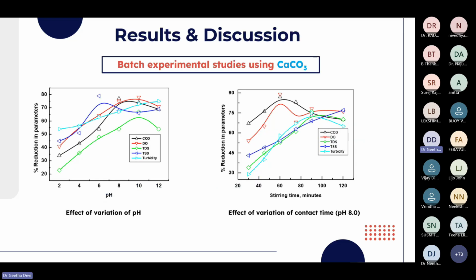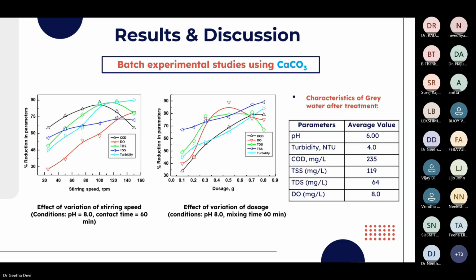And this is the experimental outcome of the calcium carbonate nanoparticles in grey water treatment. We could see that after treatment, the COD was reduced from 1811 to 235. There is a considerable reduction in other parameters also.